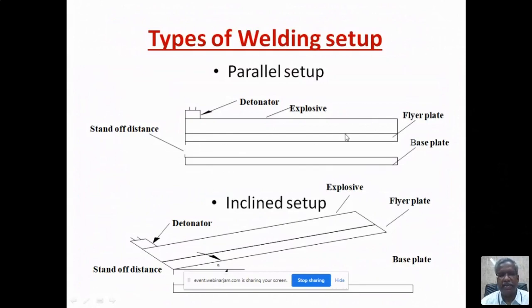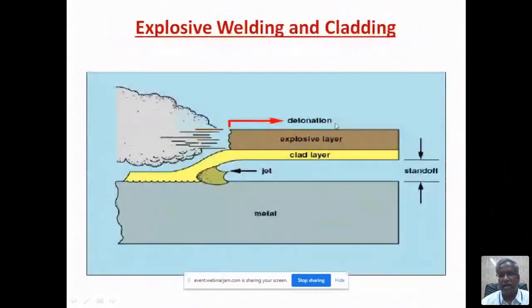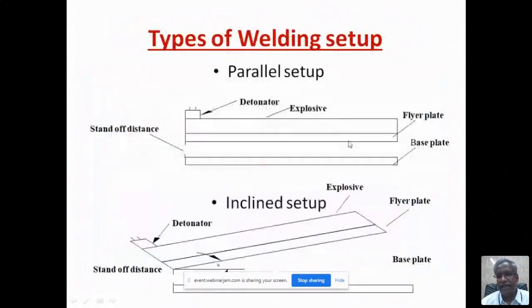So over the flyer plate, you have to pack the explosives. There are a variety of explosives available based on the detonation velocity of the explosives, and based on the weight of the explosives. There is a ratio between the explosives and the flyer plate, E by M ratio. E is the weight of the explosive, and M is the weight of the flyer plate. So if you know the weight of the flyer plate, using that ratio, you can find out how much explosive is required. So that explosive you have to take, and that will be packed throughout the entire area of